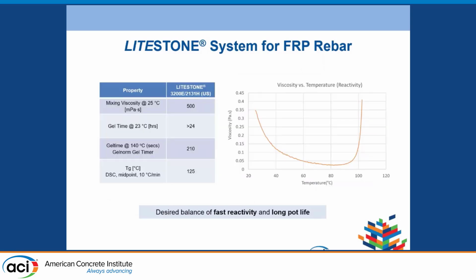So here I show the basic resin properties for the LITESTONE system. The LITESTONE 3200E and 2131H US is our workhorse for the FRP rebar applications. The mixing viscosity is around 500 centipoise. We consider this mixing viscosity a good range for fast fiber impregnation.